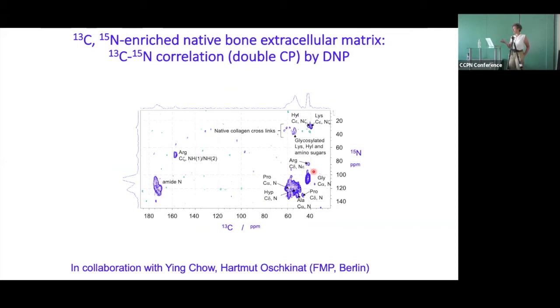For native tissues we found that gives an enhancement of signal-to-noise of around a factor of 80. That means that in your carbon-nitrogen correlation spectra you can see even very small signals — you can see the signals from collagen intermolecular cross-links. There are only about four of those per collagen molecule, and a collagen molecule is around 3,000 amino acids. To pick out four carbons specifically out of 3,000 amino acid residues is pretty neat. Dynamic nuclear polarization NMR is really making a huge difference in the solid state, particularly with proteins.